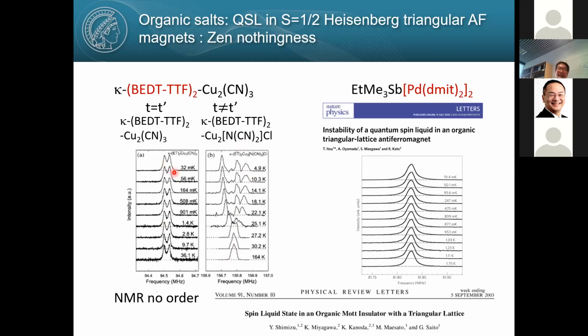And the energy scale of magnetic interaction is on the order of 200 Kelvin. So this is almost 4 orders of magnitude smaller temperature, but still you don't see any magnetic ordering. And this palladium dmit, as a quantum spin liquid candidate, again you don't see any splitting of the peak. So at least from this you can confirm absence of magnetic ordering of a spin 1/2 moment.